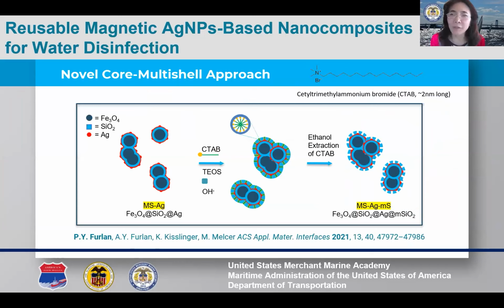After this, we bonded silver nanoparticles to MS, forming MS-Ag, by reducing silver ions attached to MS with glucose. To address the second concern, that is preventing excess silver from leaking into the water, we introduced a novel approach. For the first time, we encapsulated MS-Ag with an outer mesoporous silica shell, creating the core multi-shell nanocomposite referred to as MS-Ag meso-S. This was achieved by extending the cationic CTAB micelle templating strategy with a modified Stöber method.